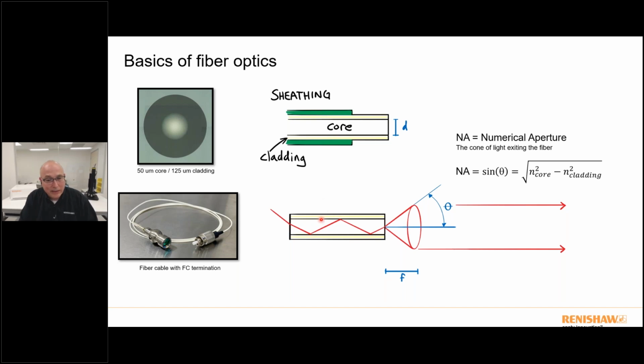The other important thing to understand is the numerical aperture of your fiber optic. Now, fibers work based off of having the core with a slightly higher index of refraction than the cladding. And so when you shine light into a fiber at a particular acceptance angle, you're going to get total internal reflection based off of that change in the index of refraction. And when that light exits the fiber, it's going to exit in a cone. And that cone is the numerical aperture of the optic. And you can figure out what that cone diameter is, what this acceptance angle is, by looking at a simple equation. So the NA, or numerical aperture, is just sine theta, which is equal to the square root of the difference between the squares of the indices of the core and cladding.